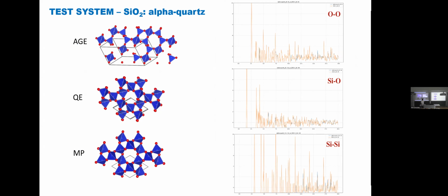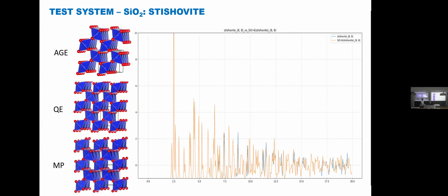And here is MP, from the Materials Project database. Here we compared these fingerprint functions for different atoms, like oxygen and silicon-oxygen, from this structure and this structure from a Materials Project structure. So it shows us a perfect match. They almost ideally match in these plots.